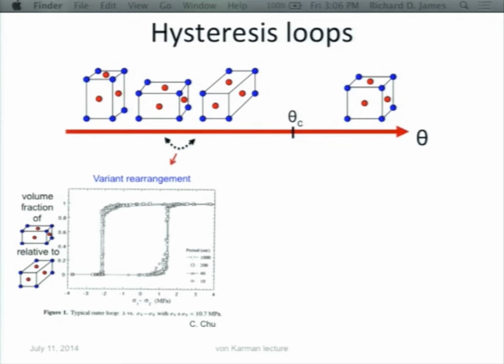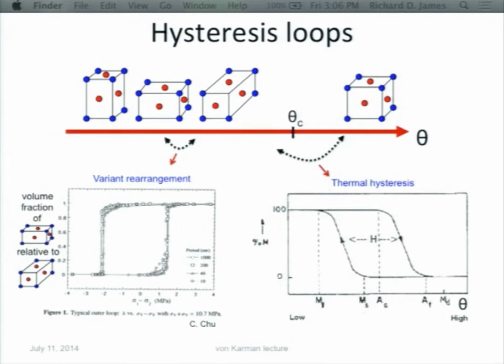which is dissipated by the material. In fact, most of my talk is about thermal hysteresis, going back and forth between this phase and any one of the 3 variants, or any microstructure of the 3 variants. You also have a hysteresis loop. People usually fit it by a parallelogram, and they define it therefore by these 4 temperatures: MS, MF, AS, and AF.